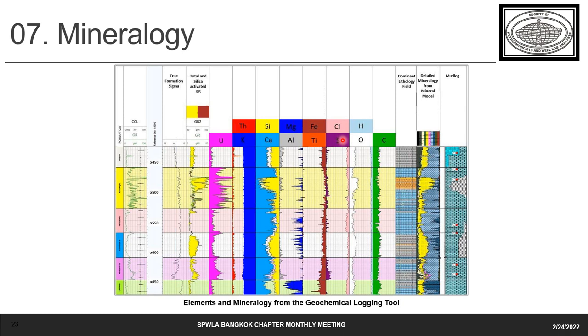The log was first evaluated qualitatively, so the statistical precision of the logging measurements plays a significant role in order to validate the tool functionality. A comparison of the Sigma logging is shown here on the left side. And we have with the blue, the main Sigma passes, and with red are the repeat passes for the detectors 1, 2, 3, and 4.